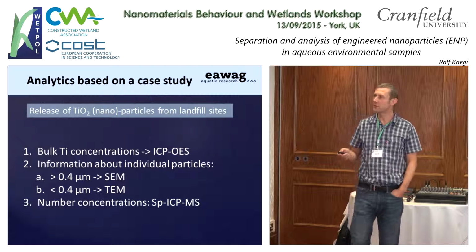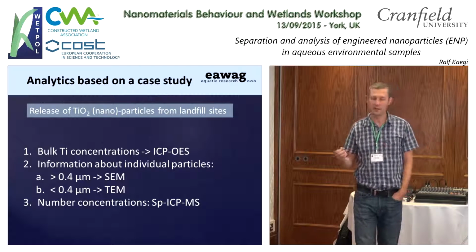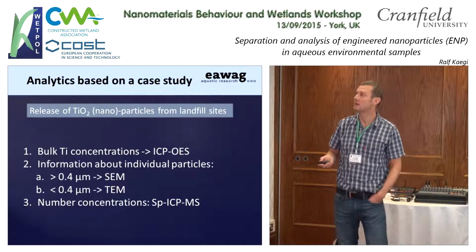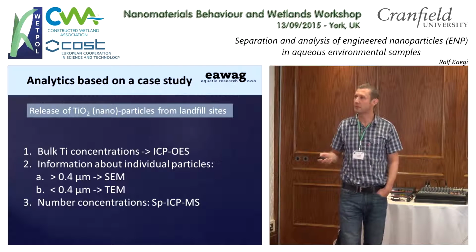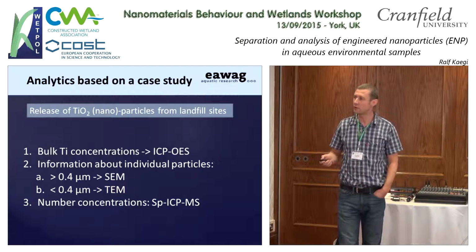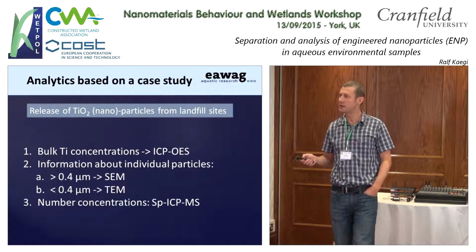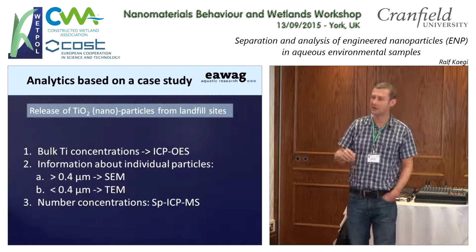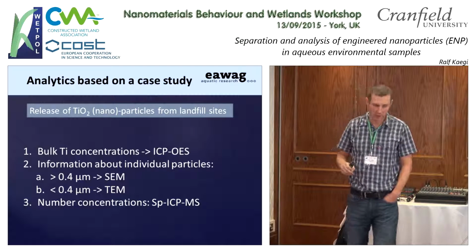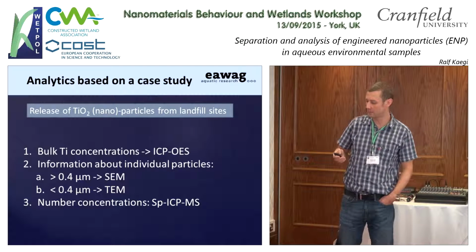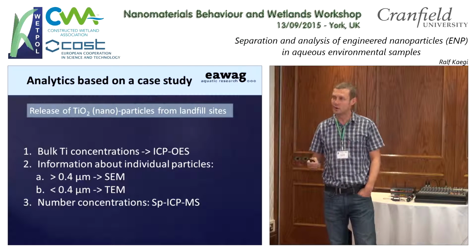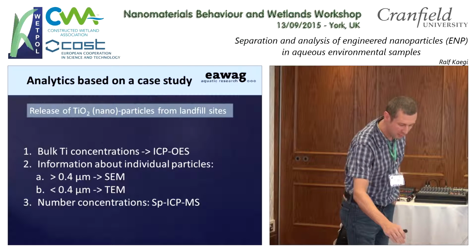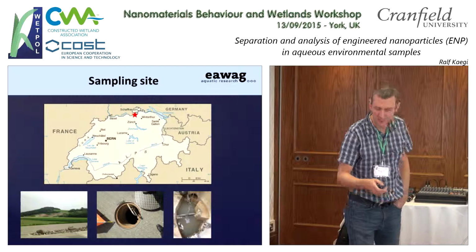So first, I will show you some data about the release of possibly nano-titanium dioxide particles from landfill sites. We wanted to assess the bulk concentration. For that, we used ICP-OES and ICP-MS. Then we wanted to get information about individual particles. We used electron microscopy, and I'll talk more about that in a few slides. And we wanted to get the number concentration of the nano-sized titanium dioxide particles. For that purpose, we used the single particle ICP-MS method.